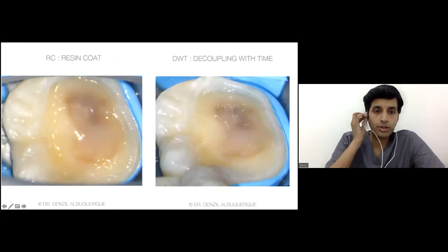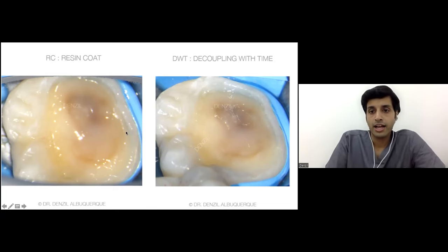Once that is done, we go in for the resin coat, 0.5 millimeters of microfilled resin, just over the immediate dentine sealing, that is dentine again. You can see clean dentine, clean DEJ. And then we go in for decoupling with time. That is nothing but wait and watch. You can have a coffee, you can fill in your notes, just wait. 5 minutes on a timer, just wait. If you're doing a proximal restoration, probably you can do the matrix band application, which will take you about 2 or 3 minutes.